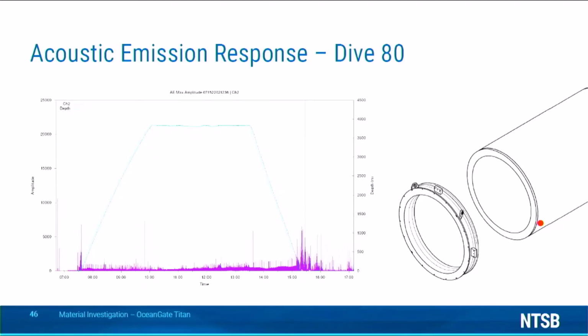So the acoustic emission response at the forward port side sensor showed a slight initial increase after dive 80 and a fall off afterwards. Here we see the response for dive 80 and its spike in acoustic activity after returning to the surface. Looking at dive 81, there was an increase in acoustic activity during the descent and once again an increase in activity after returning to the surface.